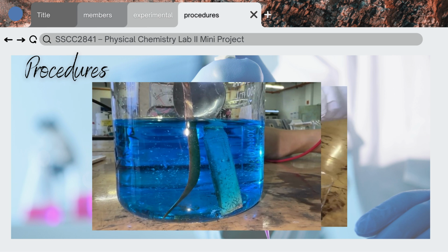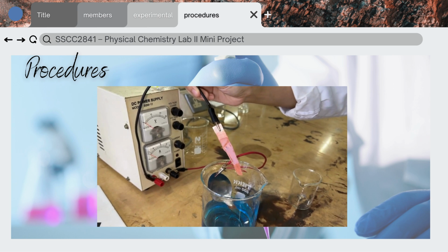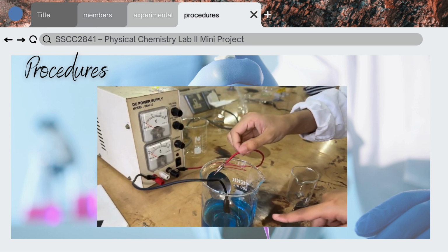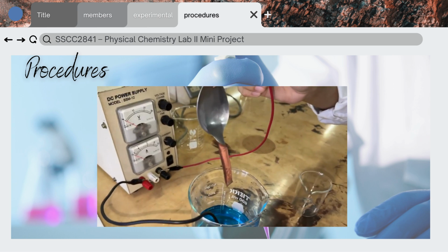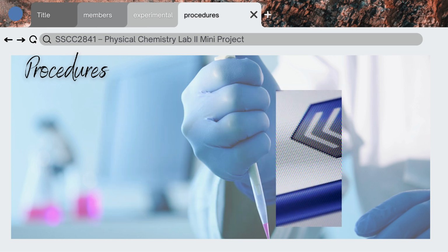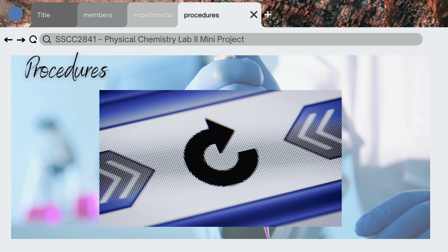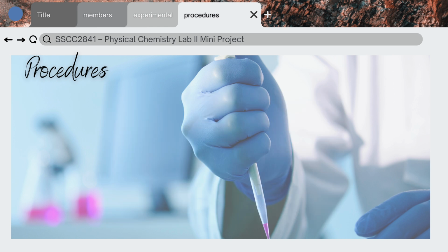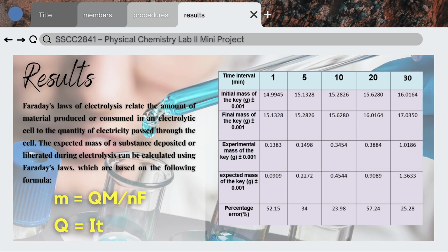After 1 minute, the wires were disconnected and the spoon was taken out of the solution. It was rinsed with acetone and air-dried for a few minutes. And then the spoon was reweighed. The experiment was repeated for 5 minutes, 10 minutes, 20 minutes and 30 minutes intervals. Based on the data obtained in this table, the mass of the deposited copper increased when the time taken for the electrolysis increased. We also measured the actual mass of the deposited copper, where we compare the mass obtained in the experiment to the expected mass to determine the accuracy of our experiment.